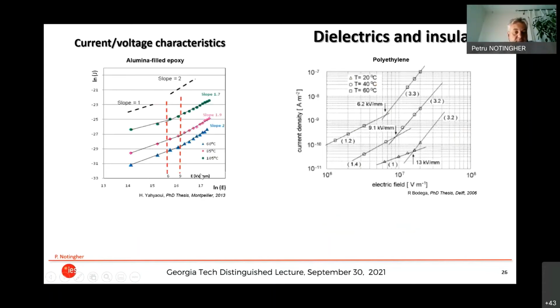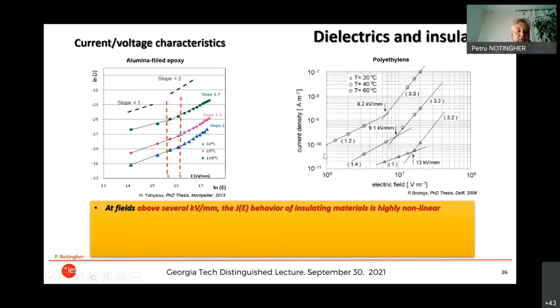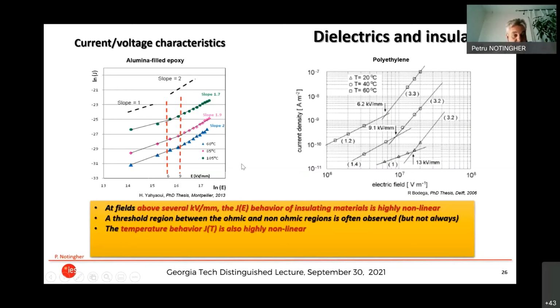Well, these are some examples that are shown here, and of course you see the slope equal to 1 in this case. Here you see a slope equal to 1, and here you see no slope equal to 1. Maybe the field is not low enough to see the low field region. So just to summarize, if the field exceeds several kilovolts per millimeter, the current-voltage behavior of the insulating material will be highly nonlinear, and you can identify a threshold region between the ohmic and non-ohmic region, but not always.